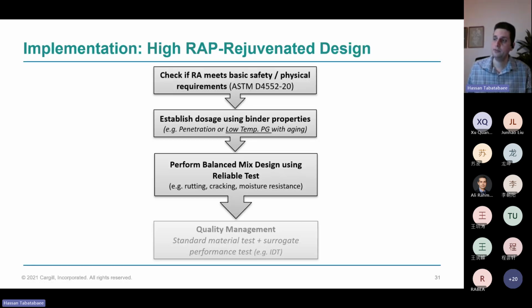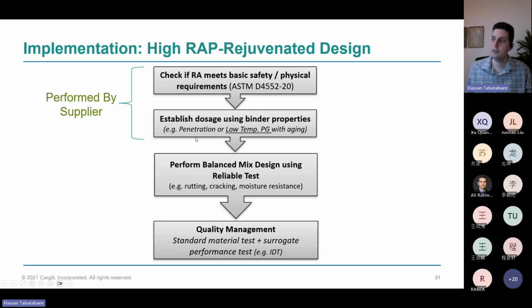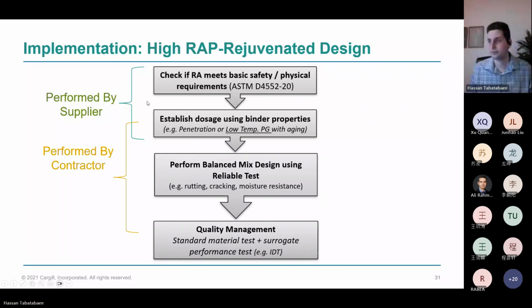For implementation, for time, I'm not going to go into too much detail, but generally there's a few steps that are happening. You look at the basic requirements using something like the ASTM table or the table in the Chinese standard. And look at determining the dosage based on the bitumen properties. That might be with penetration, could be softening point, could be with low temperature performance grade. Often the additive supplier is a big part of this conversation here.